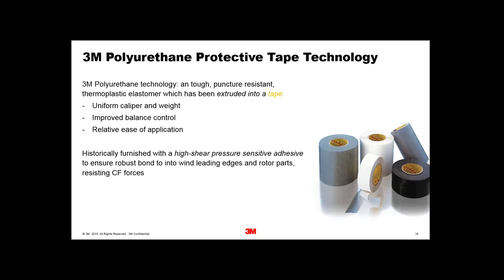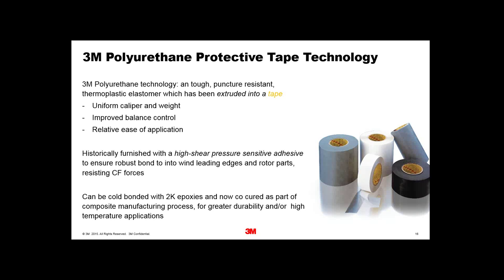These tapes are normally furnished with a very high shear pressure-sensitive adhesive that needs to be robust — not only to resist chemicals, but also the forces acting on rotating parts where there are high centrifugal forces. The adhesive's shear resistance needs to withstand those forces, otherwise it will effectively slide off the end of the rotor or fan blade. Nowadays, we've moved on from pressure-sensitive adhesives, because they only have a certain shear and are viscoelastic and prone to creep. We now have polyurethane films that can be bonded with room-temperature-curing two-part epoxy, or co-cured as part of the composite manufacturing process.